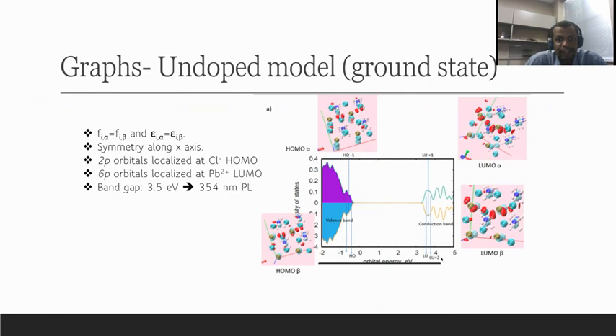About the graphs for the undoped model, like I said before, we would see the symmetry along the x-axis. And to the left, we have the valence band, to the right, the conduction band. Besides that, we can also see the band gap, like the data table showed us, around 3.5, which would correspond to a PL of about 350.